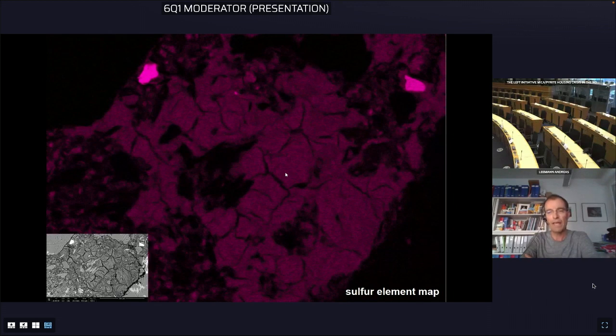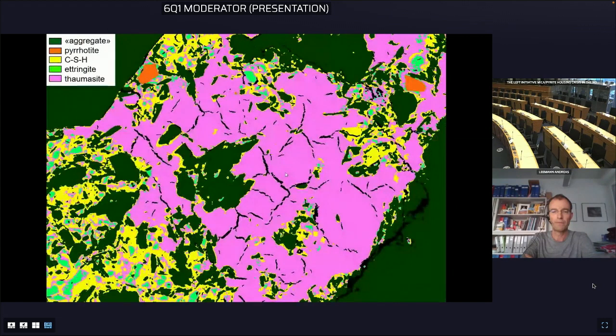Now we do the same thing again as before. We produce a phase map. Next, please. Legend upper left corner, dark green aggregate, orange pyrrhotite, yellow CSH, green ettringite, and now you see this large pink area. This is thaumasite. This concrete has gone through a severe strength loss.